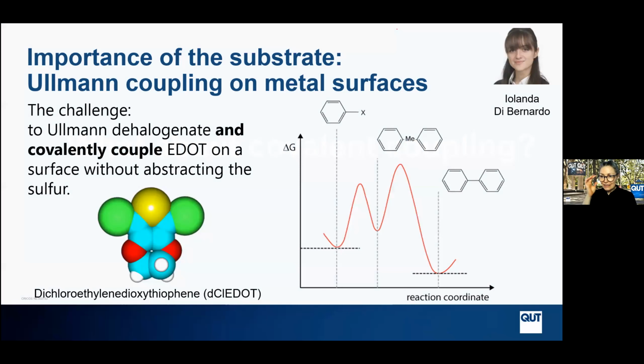So covalent coupling. We looked there, of course, at the control of reaction, then self-assembly. And of course, another ethos we can use is to pursue covalent coupling. And this is Iolanda's work, and Iolanda's watching, so I hope I do a good job of relating it. Iolanda worked on this molecule here, which is dichloroethylene dioxythiophene, which is dichloro-EDOT. If we successfully polymerize it, we produce a well-known organic polymer called PEDOT. This happens through a process called Ullmann dehalogenation, which is schematically represented at the right of the slide here, where what we're interested in doing is breaking a carbon halogen bond, which will then allow the formation of an organometallic, which can then be converted to a covalent polymer.